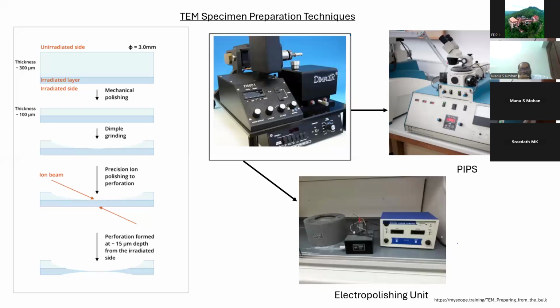So the first thing is to make a 3 mm disc. I hope many of the mechanical engineers here are working on steels or high-end alloys. For them, and even if they are from a chemistry background, a 3 mm disc is needed. For chemical engineers, chemists or physicists, if they are interested in seeing nanoparticles, they will be dispersing them on a copper grid. Whereas metallurgists or mechanical engineers will be more interested to make a 3 mm disc first. A 3 mm disc can be made by wire EDM, or a mechanical punch. So once you get this specimen, you have to polish it.